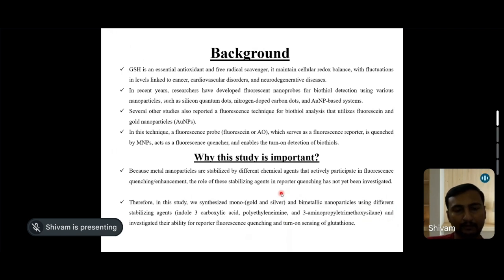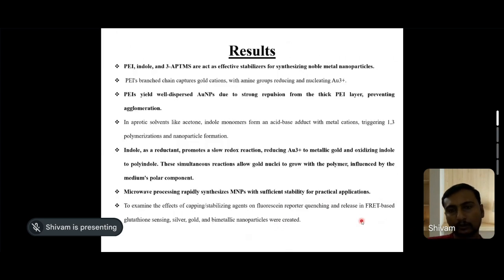So therefore, in our study, we synthesized monometallic gold and silver, and bimetallic nanoparticles using different stabilizing agents as I discussed, indole-3-carboxylic acid, polyethylenimine, and 3-APTMS, and investigated their ability for reporter fluorescein quenching and turn-on sensing of glutathione. So in results, we found that polyethylenimine, indole, and 3-APTMS act as effective stabilizers for synthesizing noble metal nanoparticles such as gold and silver.